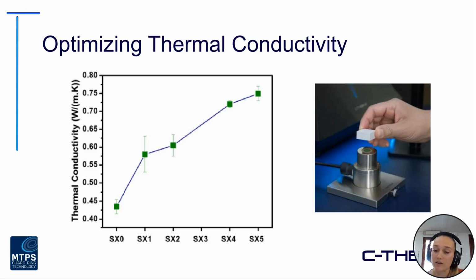As you can see, it requires a very small sample. It's quite the easy setup. You basically just place the sample on the sensor, you place a weight on top, and that's about it. So quite an easy method, very fast, very repeatable between users. We see a lot of groups prefer this method, especially the academic groups where they may have many students coming through the lab and need a very quick, easy method to test thermal conductivity. So the MTPS is quite popular for studies such as this.